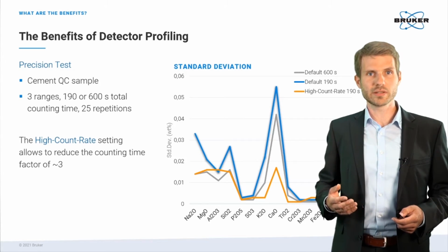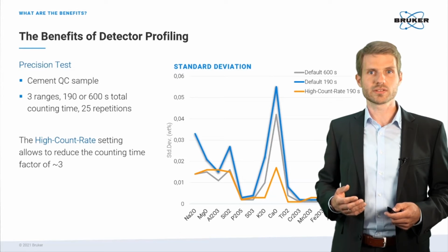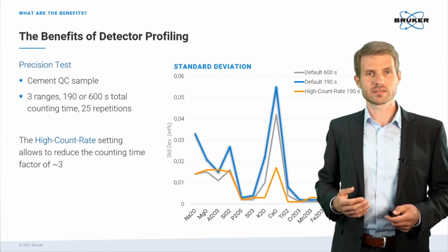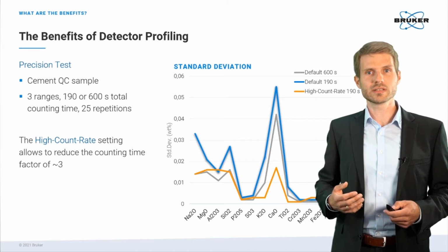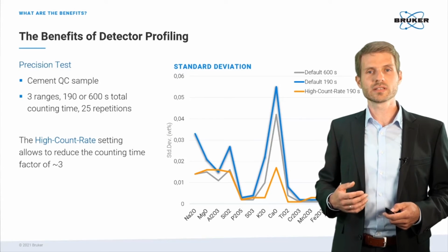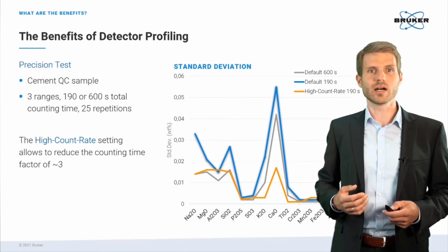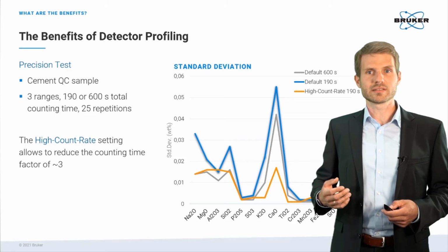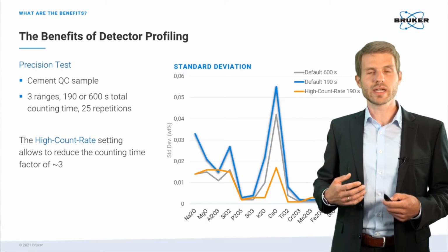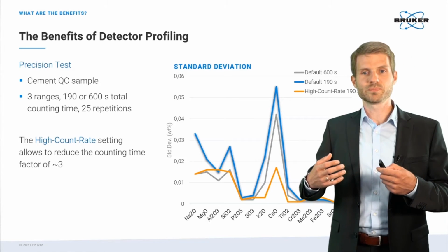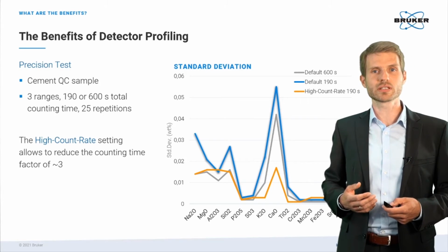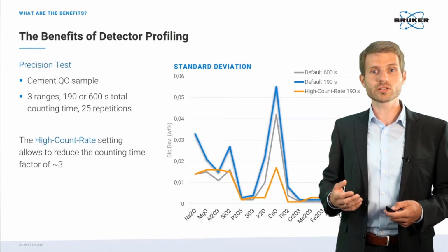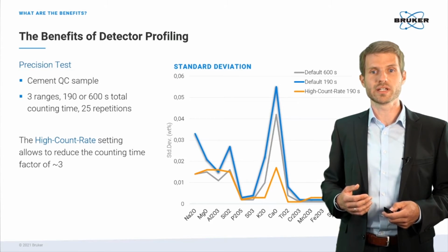Here I show the results for 3 examples. In gray, you see the result for 600 seconds with default settings. In blue, you see the results for 190 seconds with the default setting. And in orange, you see the results for 190 seconds with the high count rate. As you can see clearly, this highlights that you can decrease the counting time by a factor of about 3 without compromise on the precision of your measurement by choosing the high count rate setting for cement and related applications.